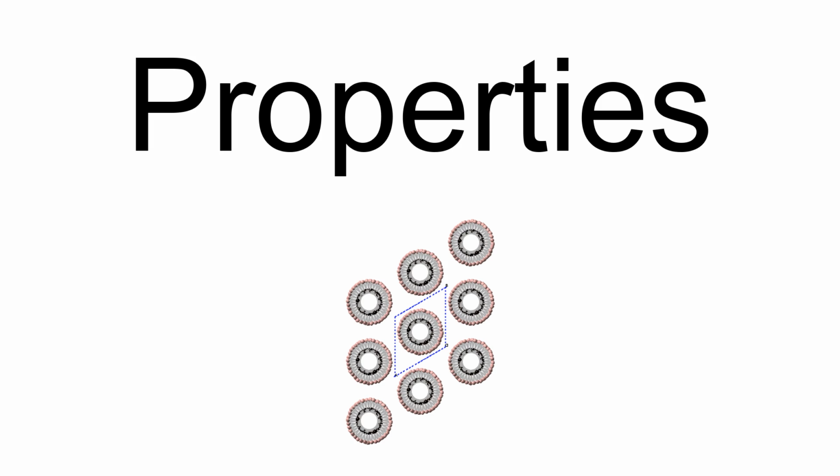Much as graphite exfoliates into sheets and ultimately graphene, nanothread crystals exfoliate into fibers, consistent with their structure consisting of stiff, straight threads with a persistence length of 100 nm that are held together with van der Waals forces. These fibers exhibit birefringence, as would be expected from their low-dimensional character.